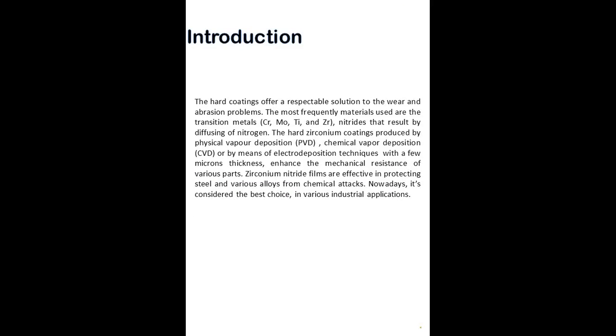Hard coatings offer a respectable solution to wear and abrasion problems. The most frequently used materials are the transition metal nitrides, such as chromium nitride, molybdenum nitride, titanium nitride, and zirconium nitride, which result from the diffusion of nitrogen.